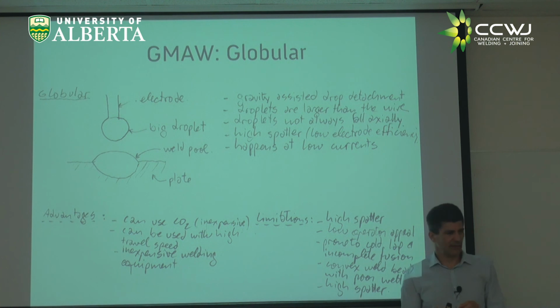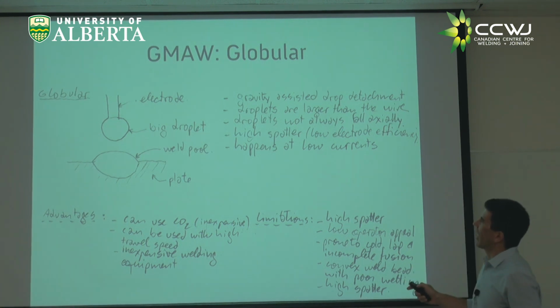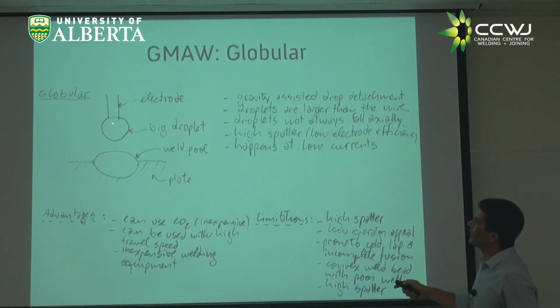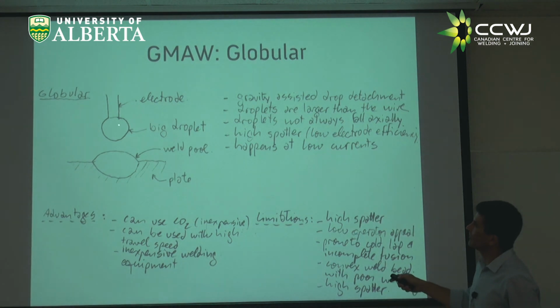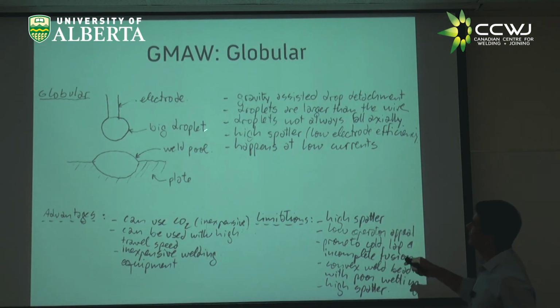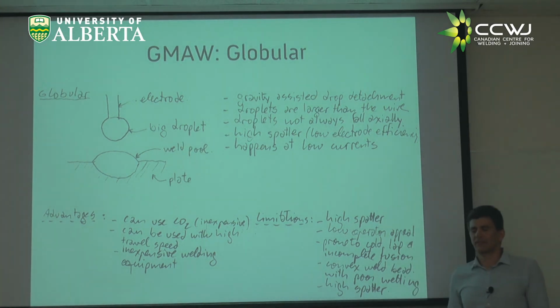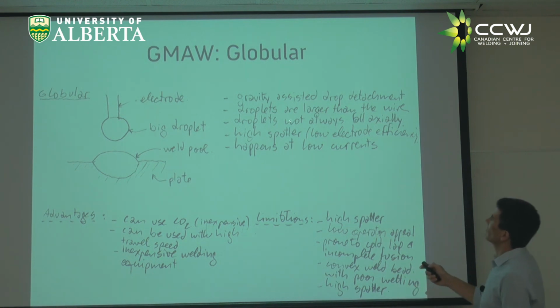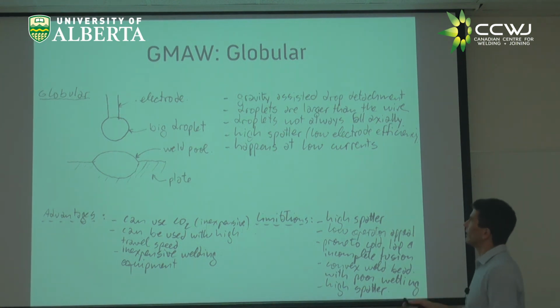All right, so we have a few more minutes, and I want to go over these metal transfer mechanisms. So let's start with globular, right? We already mentioned that it's like a drippy faucet in which you have the big droplet that detaches by its own weight. There is a definition that says globular is when the droplet is bigger than the wire. You know what? I don't care about that definition. Typically, it's true. But what really matters is that the physics of detachment is by weight, right? Which typically happens to be the droplet bigger than the wire, right?